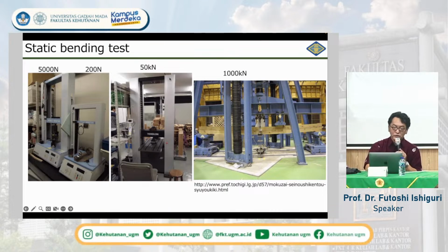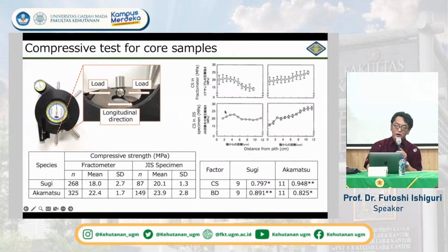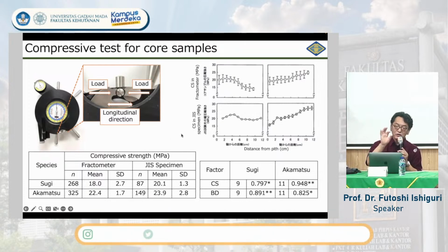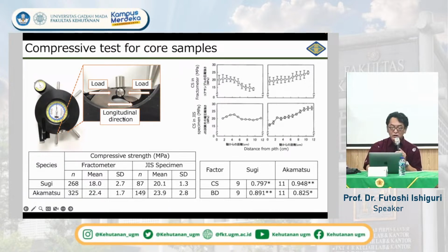In my laboratory, we have three testing machines: 5,000 Newton, 200 Newton, and 50 kilonewton. And sometimes we focus on full-size specimens. At that time, we collaborate with the prefecture, the local governmental forestry center, and we conducted bending tests. And sometimes we cannot collect the trees. We don't get permission to cut. At that time, we collect very, very small samples, looking like a straw shape. By using those straw-shaped samples, just 5 millimeters in diameter, with this machine, we can estimate the compressive strength.